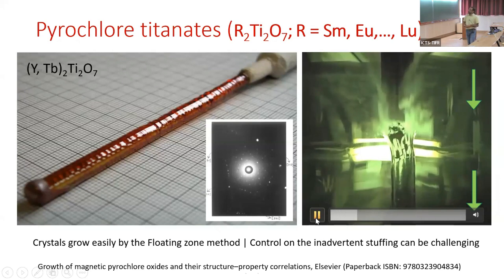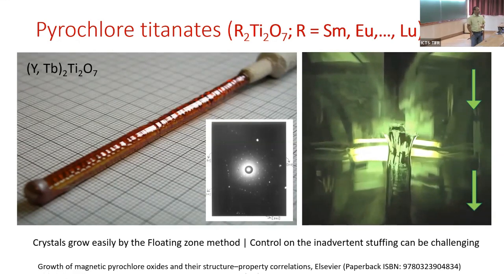So this is how the crystal growth is done in a float zone furnace. Basically, you take the light from the halogen lamps and you focus it tightly over a very small volume. This volume is typically 5 to 6 millimeter in diameter and about 7 to 8 millimeters in length. You have 4 lamps. Each of these lamps is about 1 kilowatt. So 4 kilowatt of power, tightly focused over a very small region of space. And that is where you bring your material, which is to be grown as a single crystal.